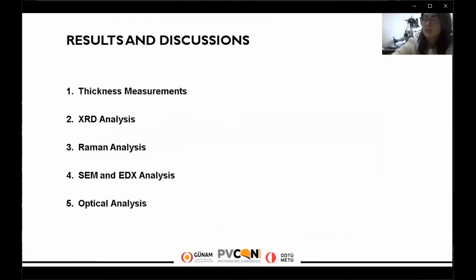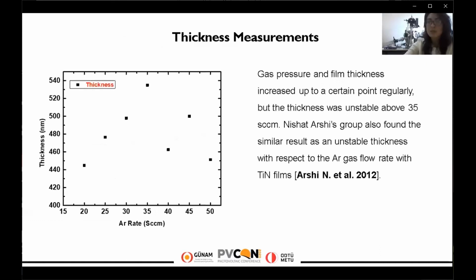Yes, now the results and discussion part. I will talk about thickness measurements, XRD, Raman analysis, SEM and EDX analysis, and finally optical analysis. Here we see the thickness measurement graph. You see it looks like an unstable graph because until 35 SCM, thickness increased up to 30 points regularly, but the thickness was unstable above 30 SCM.